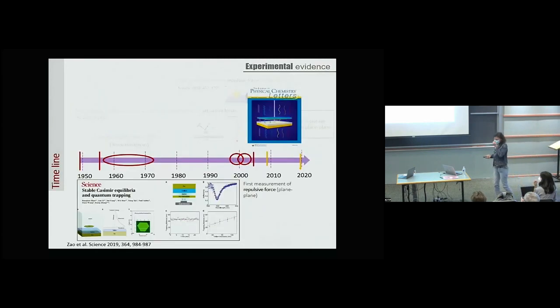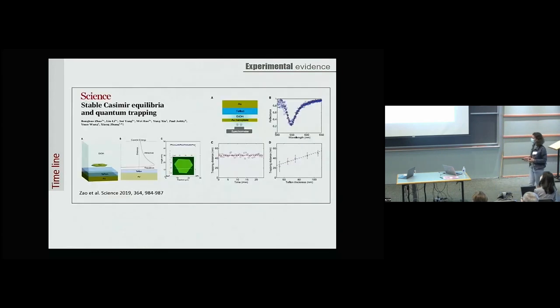And then it just happened, as it always happens, or many times happens, in science. The same idea was demonstrated experimentally by the group of Professor Xiang Zhang here in Berkeley. So basically, instead of doing this macroscopically, they went to micrometers. So they had a flake of gold in ethanol on top of a substrate, which is gold with this Teflon layer. So they made these spectroscopic measurements. They fitted everything, and by changing the thickness of the Teflon, in our case the silica, they could tune the equilibrium distance of this levitating gold flake.